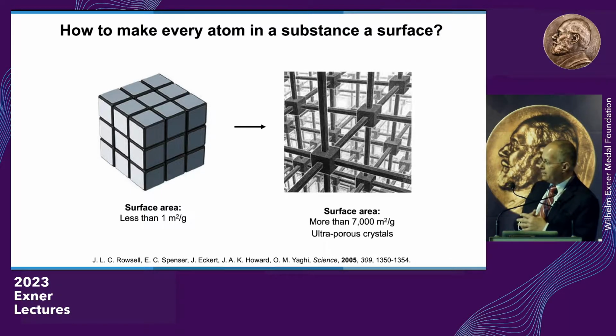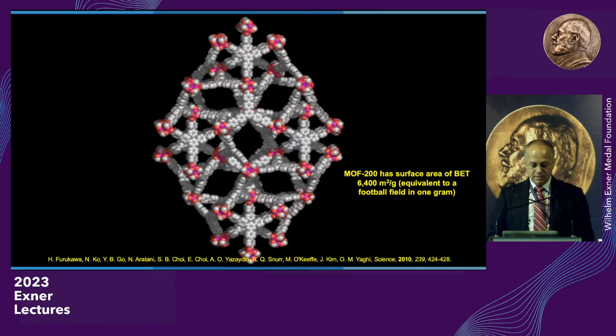This is another MOF made from metal oxide units here in pink and organics. And we know from crystallography of gases in the pore that everything you're looking at, whether it's the metal oxide units, the edges of the 6-membered rings, or the faces of the 6-membered rings, are actually binding sites for molecules like hydrogen, water, CO2, and other gases. That's what makes them so porous. This particular structure has a surface area of 6,400 meters square per gram.